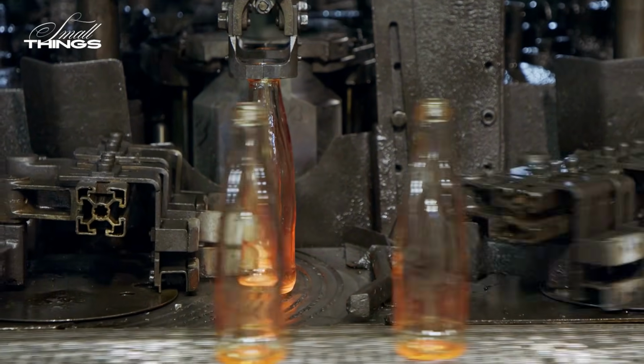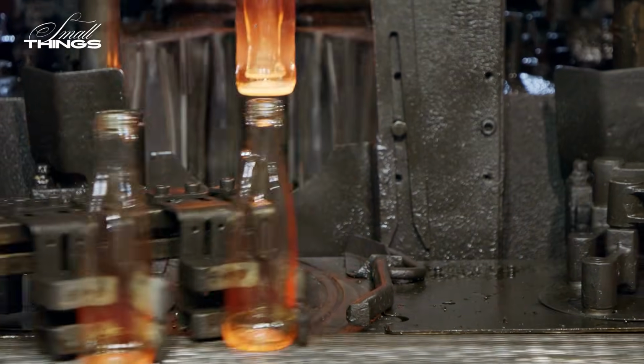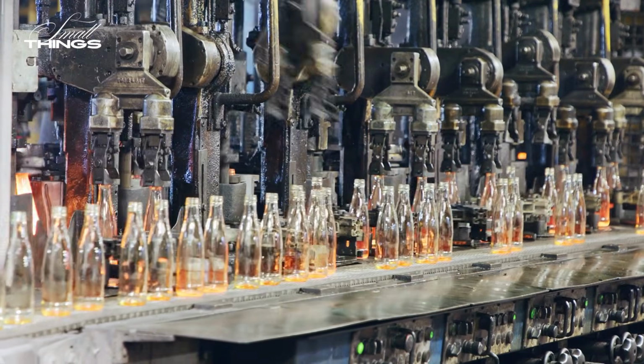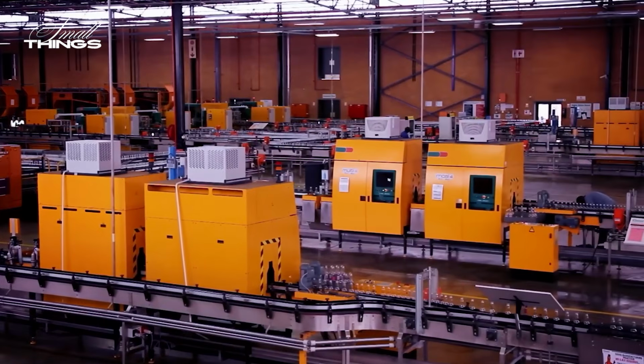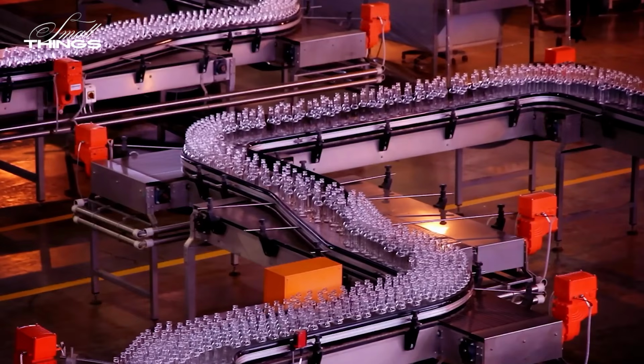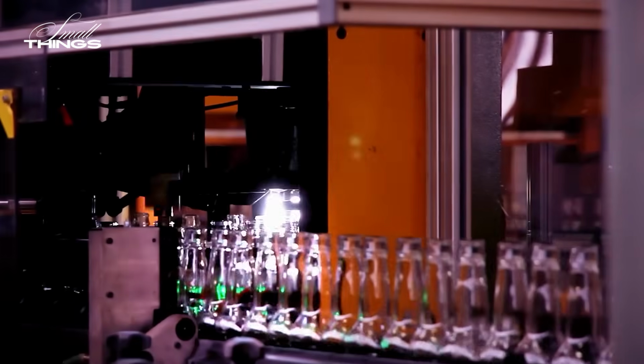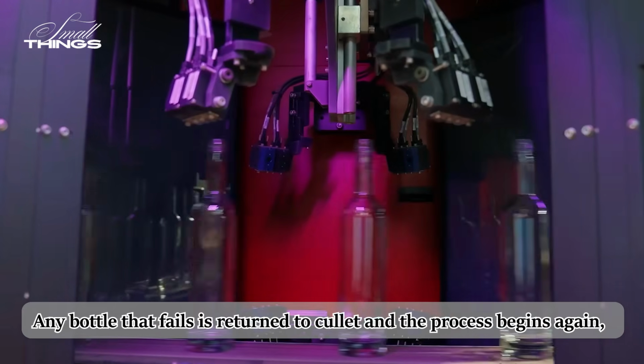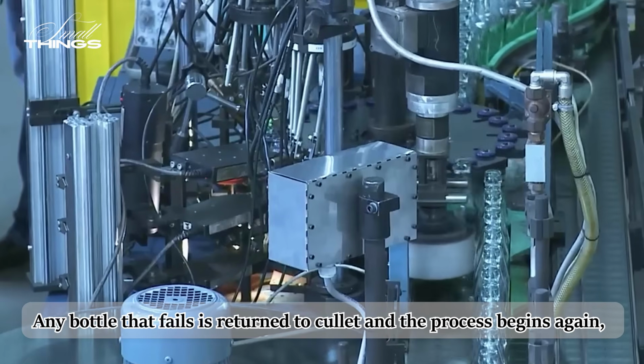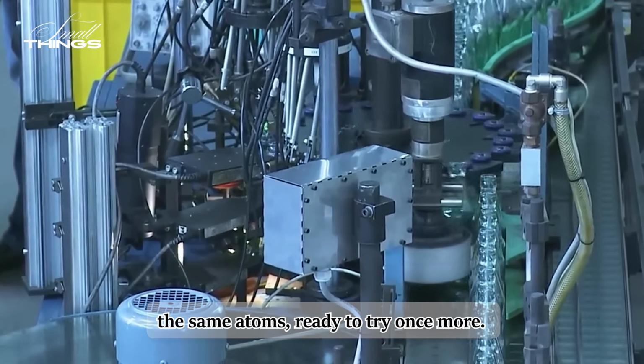It comes out glowing red, travels through a slow annealing oven where internal stress is gradually released, then passes under high-speed cameras checking for cracks, bubbles, and dimensional errors. Any bottle that fails is returned to cullet and the process begins again, the same atoms ready to try once more.